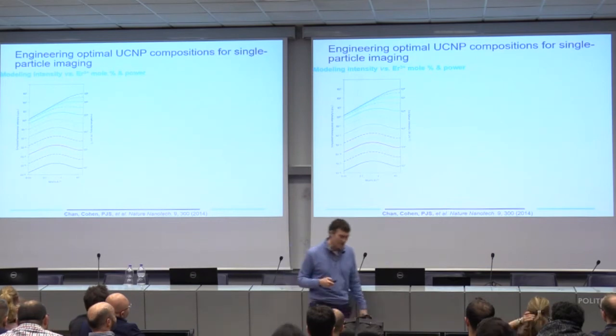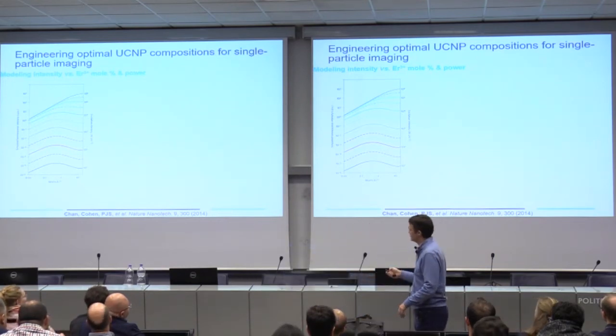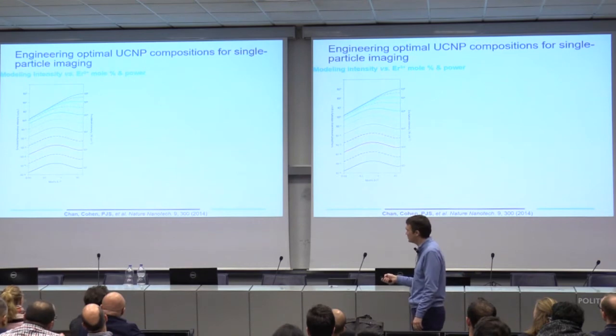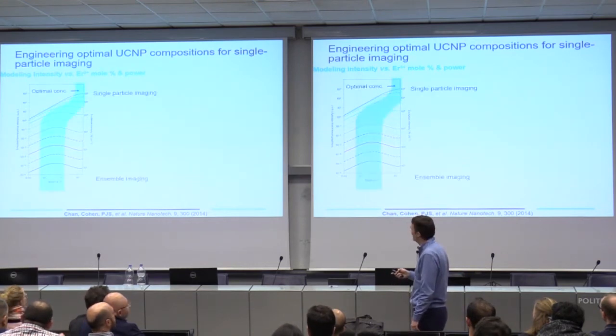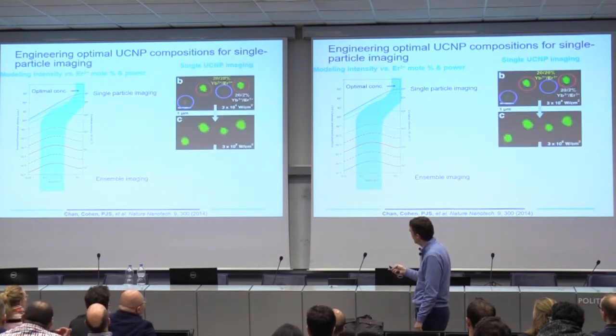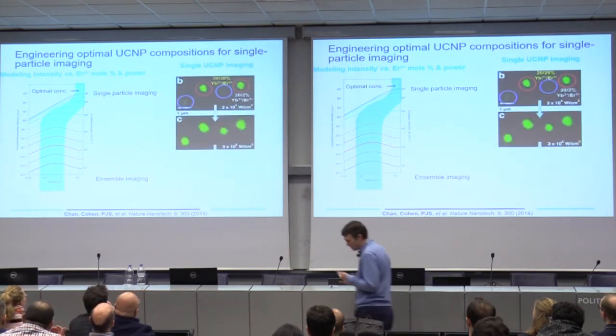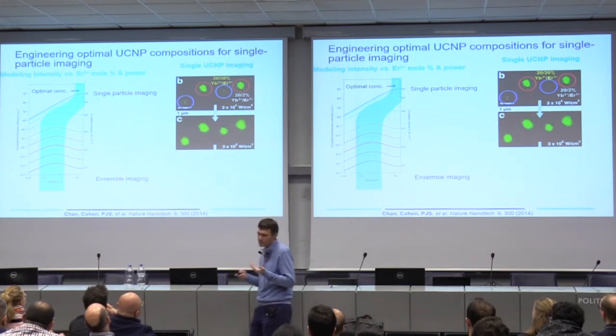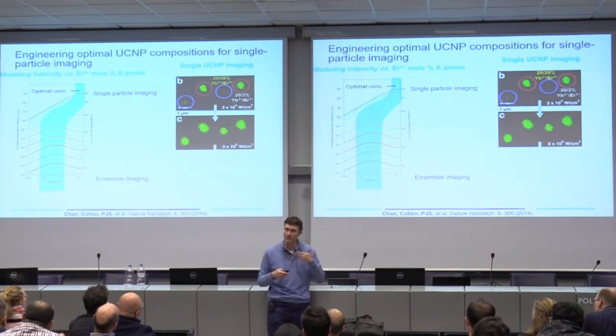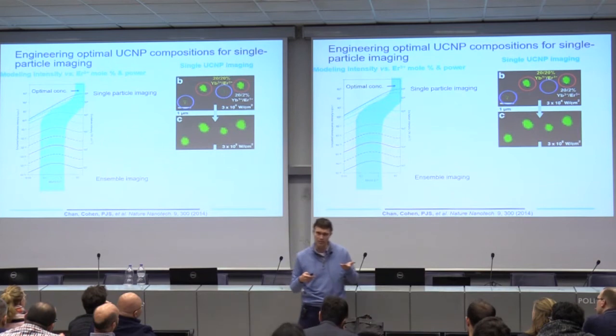Are the 2%s the most optimal? And of course the answer was no, not at all. In fact, what you really wanted was more concentration of emitters in your material. And once you go in and put more emitters in your material, the first thing we did was increase the emitter concentration by 10 times. So we went from 2% to 20%, 20% erbium.